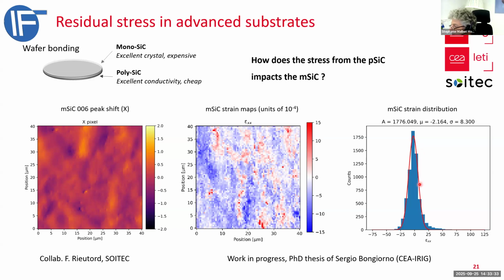So you can also have very good statistics of the strain distribution. You have the mean value, and you can measure with the Laue diffraction the absolute lattice parameters. And this a0 is a textbook value. But we can measure this a0 value from the experiment, and we can also measure the distribution, the width of that.